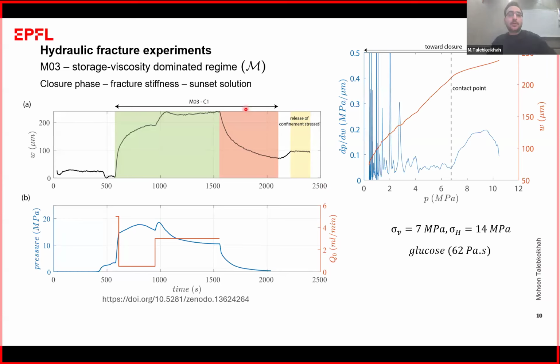So when we have the opening at the closure phase and also pressure at the closure phase, we are going to plot them versus each other. Here you can see the opening, and here is the pressure. In addition to all of this, I showed the derivative of the pressure with respect to the opening, that is denoted as the stiffness of the fracture, in blue. And I could see that at a specific point, we will have a kind of linear behavior and a kink in the behavior of the stiffness of the fracture. So we associate this point with the point that fracture contact happens, and afterward we will have an elastic behavior after the closure. So we will pick this point as our closure pressure and closure time.